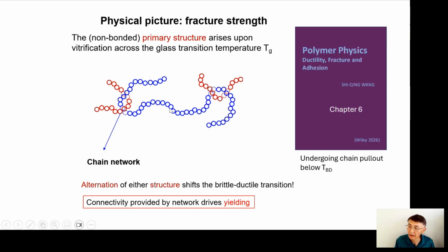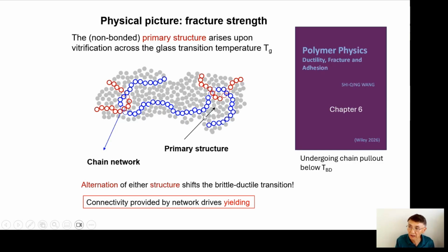And this unit repeats itself millions of times when you have a macroscopic sample. And you are just holding two ends of the sample, trying to stretch. As you do, this network, of course, will also try to undergo displacement. So it's moving along, trying to drag along the dormant segment that's in there. And the question is really whether you are successful in wakening up this dormant segment to participate in the shape change. See, when you elongate, what happens is, if volume is conserved, if you elongate, the transverse cross-section must proportionally contract, shrink. And that requires the whole sample to have enough mobility.